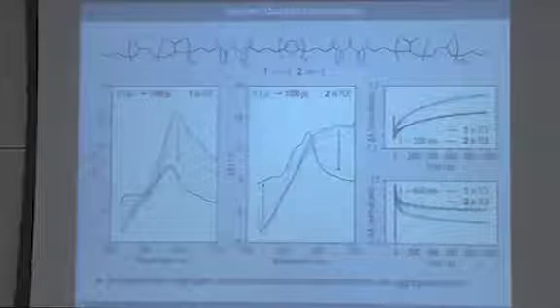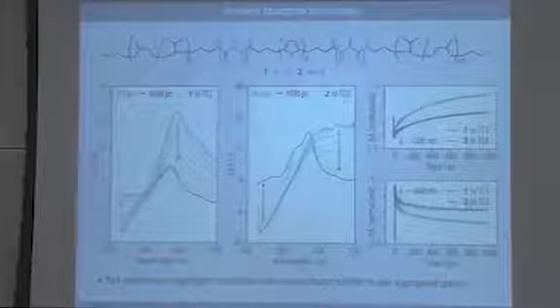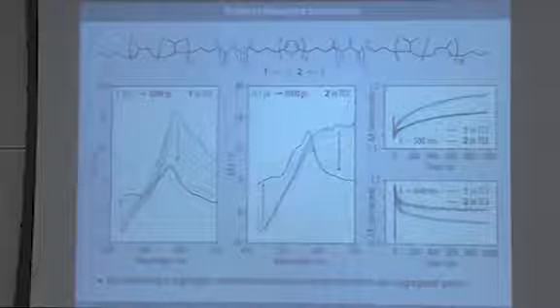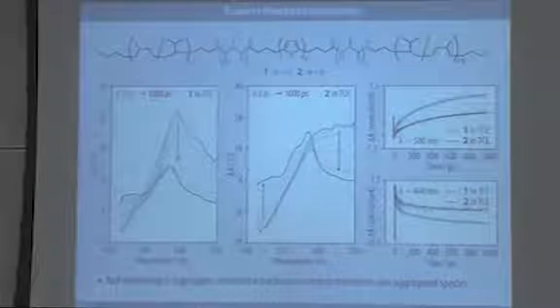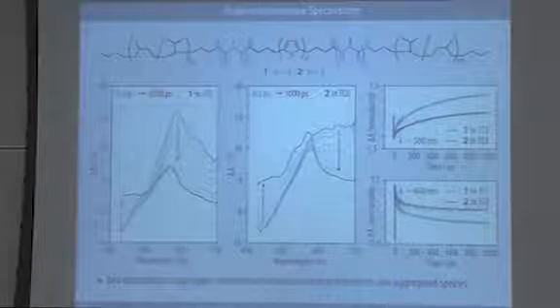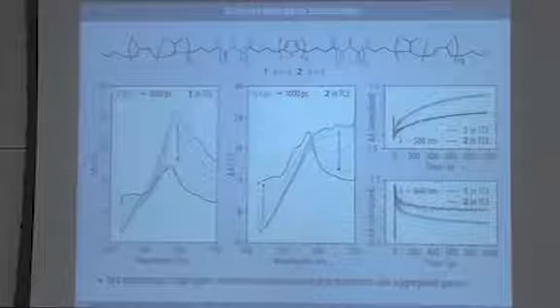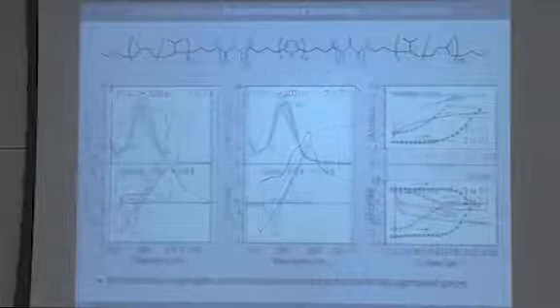Please consider that the axes are actually different in this case. So how we interpret that is that there must be, after initial excitation, an additional pathway for decay. We could so far exclude that it's singlet-singlet annihilation or energy transfer. So we believe it's charge transfer, the nature of which we're not entirely sure of as of yet. But I will comment on that in more detail at a later point.